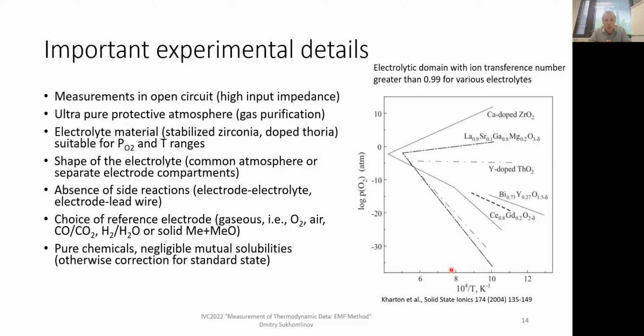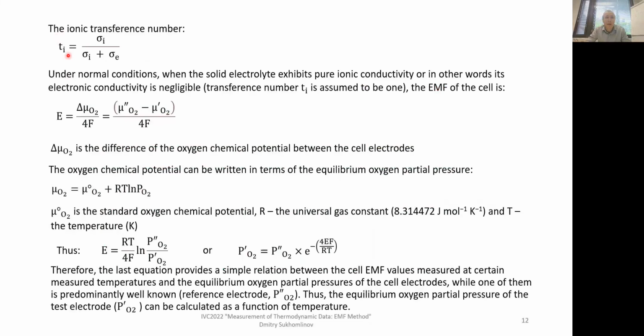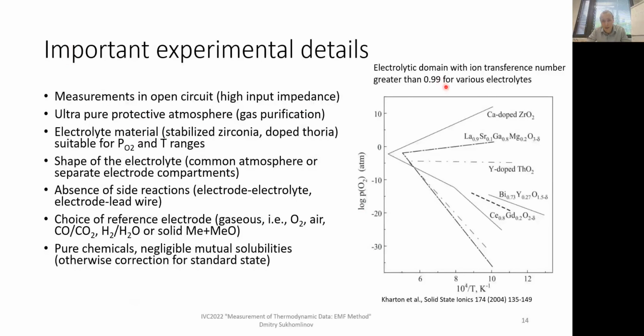Then we need to choose suitable electrolyte material. The graph on the right side shows the domain or range of temperature and oxygen partial pressure where these common oxygen solid electrolytes behave as pure ion conductors, referring to this number, the ionic transference number t_i of 0.99. This is a practical, acceptable deviation from 1.